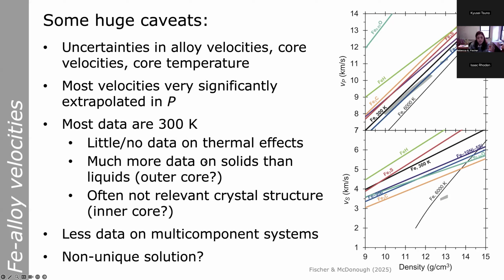This also means we have much more data on solids than liquids, which again makes it difficult to compare the data directly to the outer core. And because of these large extrapolations, they're often not on the relevant phase to apply to the inner core. And again, there's less data on multi-component systems, although not none. And this kind of exercise also will probably not give us a unique solution to what the core's composition is, but it will certainly help us narrow it down as we continue to push the techniques to get more data at higher pressures and temperatures.